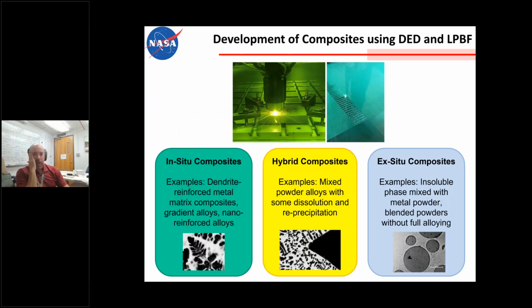So some of the alloy development things that we're really interested in is developing metal matrix composites. And so here's 3 examples of the metal matrix composites that we develop. There's in situ, where you can melt phases together and you can form dendritic phases that solidify from the liquid. You can do hybrid composites where you partially dissolve particles, reprecipitate them, and you've got 3 phases present. We also look at ex situ composites where you have insoluble phases inside of a matrix. And these can all be printed both with powder bed fusion and with DED for various applications.